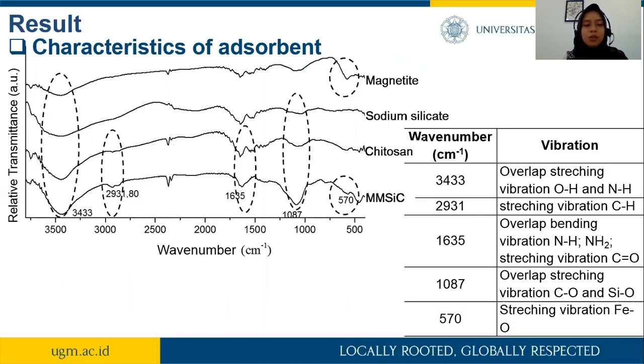So we enter our result. There is characterization of the adsorbent with infrared spectrophotometer. Based on the obtained FTIR spectra, the wide characteristic absorption band at 3433 overlaps the stretching vibration of hydroxyl and amino. And then at 570, we can see the stretching vibration of ferric and oxygen atom.